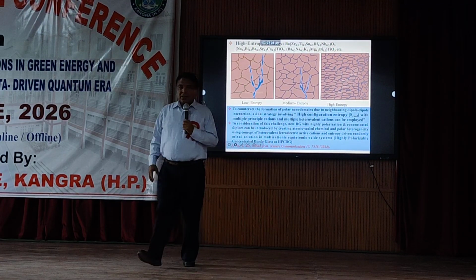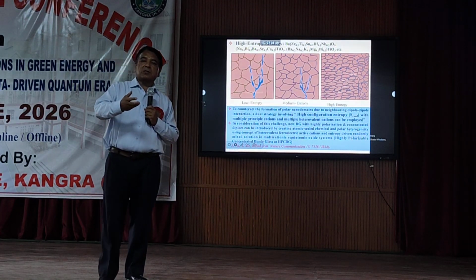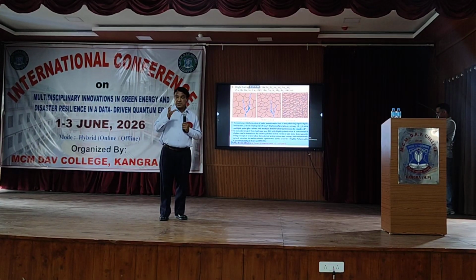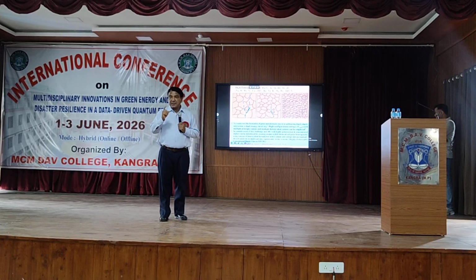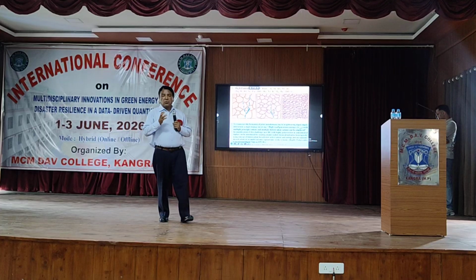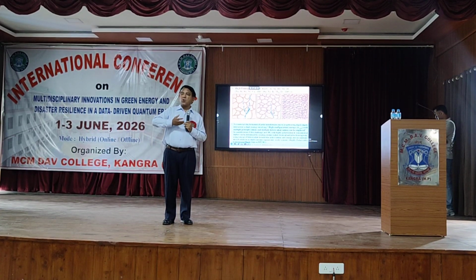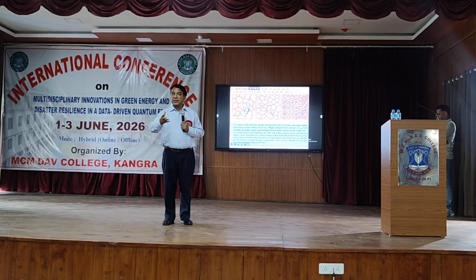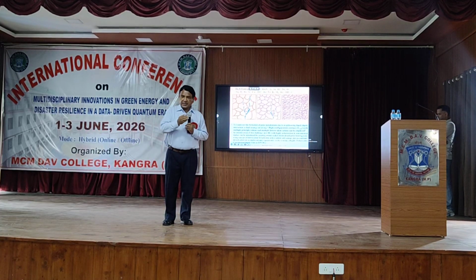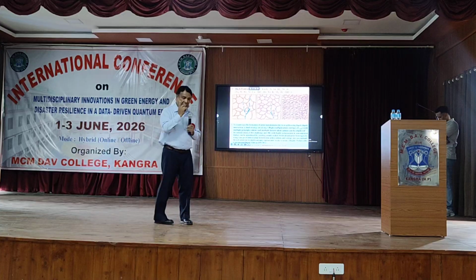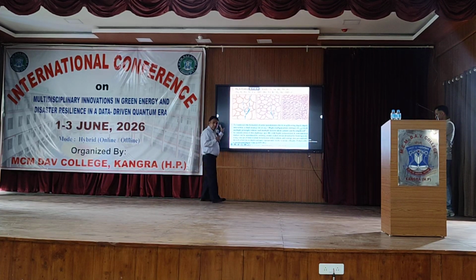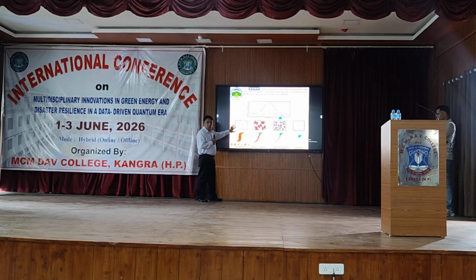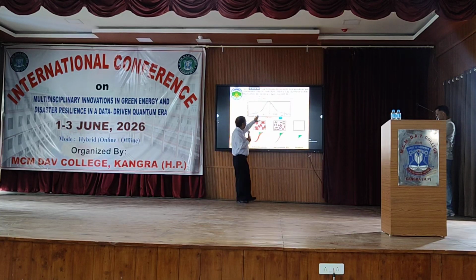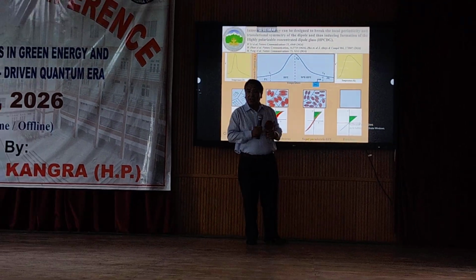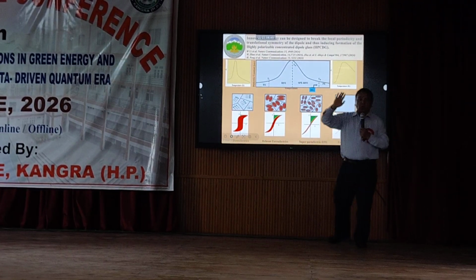So this is low entropy, this one is medium entropy, and the last one is high entropy. What is the basic difference? The conventional way of doping depends upon how much an element is soluble in that particular material. So this high entropy design is modification at the atomic level, meaning thereby you will get a high value of entropy if you choose more elements of different atomic radii to be substituted for the mother atom, resulting in a very divergent, highly polarized, concentrated dipole glass. So meaning thereby this is the story beyond relaxor ferroelectric, which we can see here by this beautiful picture. Already I have discussed these: ideal ferroelectric, ferroelectric, relaxor ferroelectric, superparaelectric relaxor ferroelectric. What happened is that here in the paraelectric state the polarization is low. There is no question of